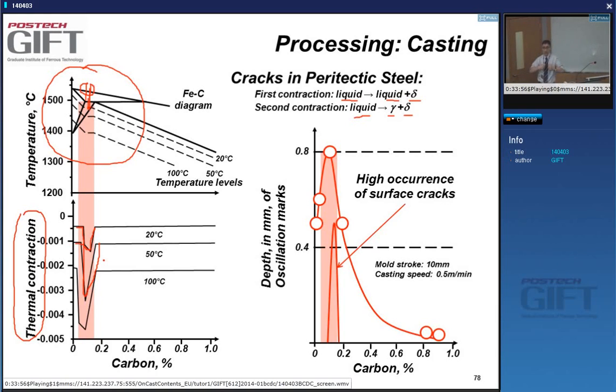You have a surface, and it contracts. The center doesn't contract, so you've got stresses. This is material at between 1400 and 1500 degrees C, and I just told you the strength of this material is very, very low. So small cracks can develop at the surface. When people measure the occurrence of surface cracks, they always observe a very large maximum at 0.1 to 0.2% of carbon.